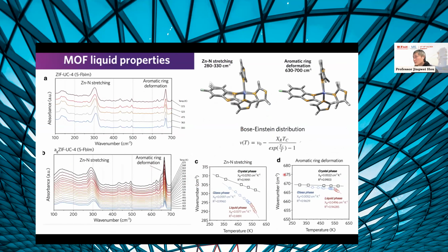I think my former supervisor and also collaborator, Tom Bennett, has actually done quite a lot of study on the melting mechanism for the MOF. I would say it's somewhat similar to the melting of other materials. You have to provide enough energy into the system. In this case, it's for the framework to allow the transition, breakage, and recoordination of the bonding within the framework. But this has to happen very quickly, otherwise you will probably lose the ligand by thermal decomposition. So that's basically the fundamental mechanism of the melting.